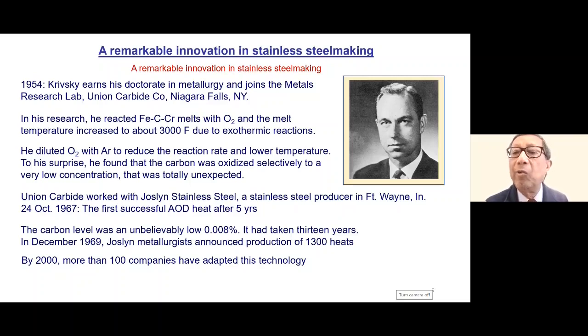So he thought he would reduce the oxidation rate. After all, rate has nothing to do with the thermodynamic equilibrium. So he diluted the oxygen with argon, and he expected that the rate of reaction would be lower, and so he would be able to do isothermal experiments at lower temperature.